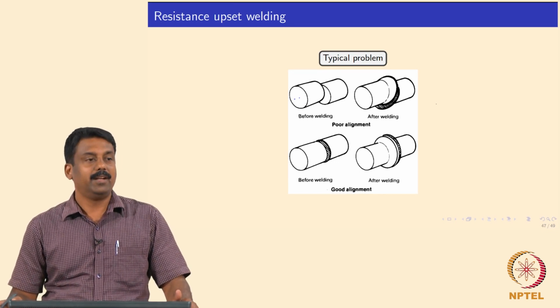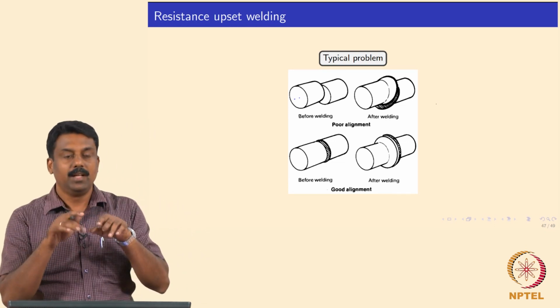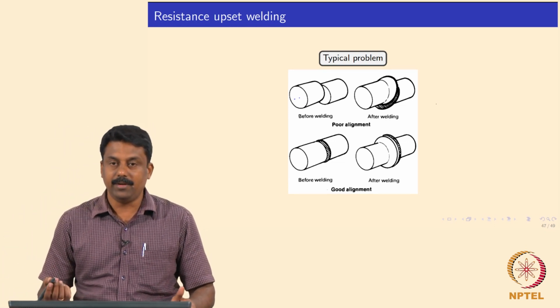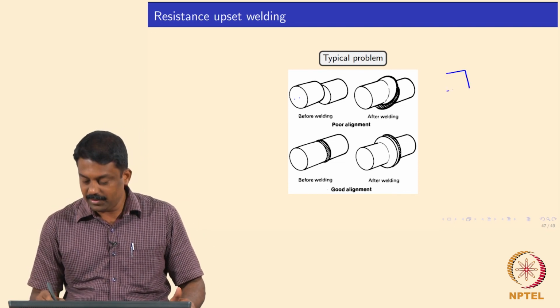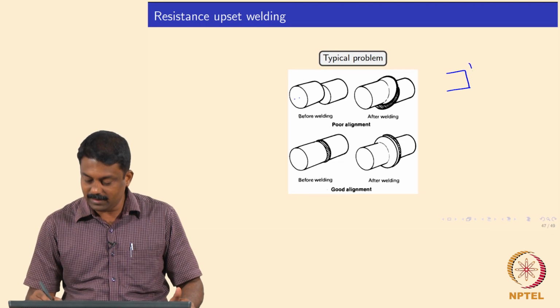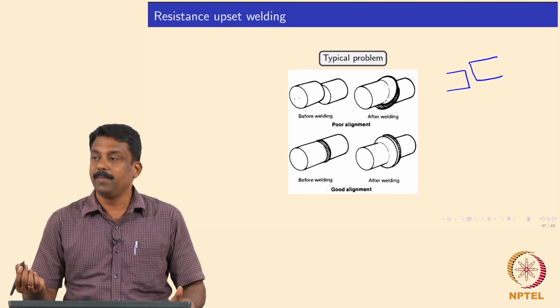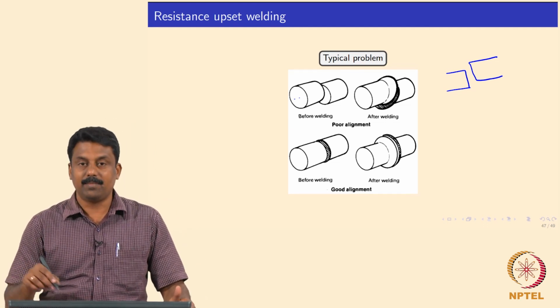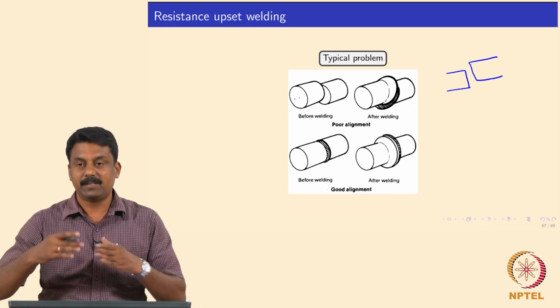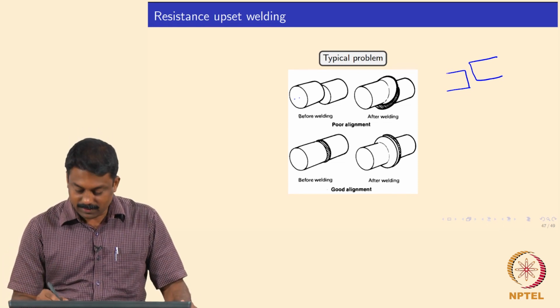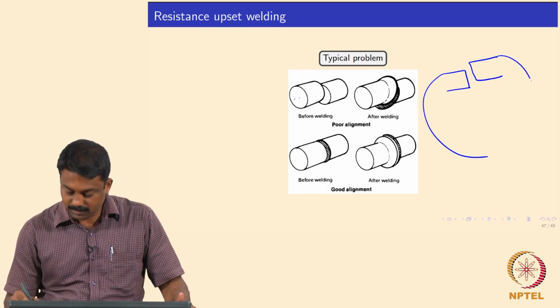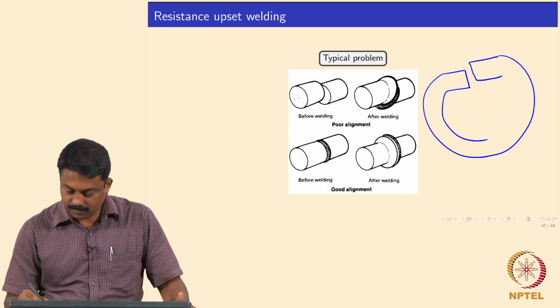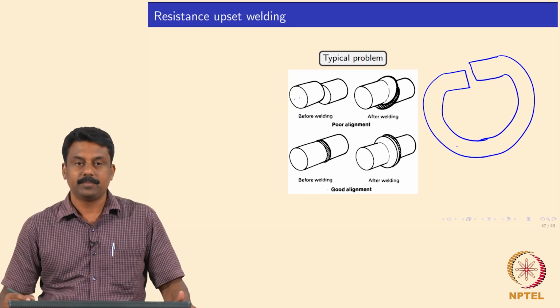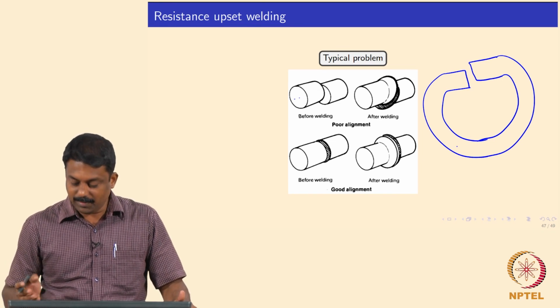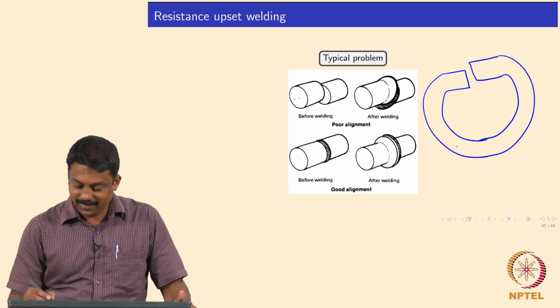And this is a very common problem even in wheel making. If there is a small misalignment and you have, say, 2 mm, 2.5 mm sheets that are commonly used for wheels, and this is one edge of the wheel, and the other edge should be perfect. If the other edge is somewhere here, because the most common problem in the rolling of circular pipes is spring back. If the spring back is not controlled properly, something like this, a cross section, it's not symmetric. Imagine this is a toy car, so the wheel is like this. Now if there is a spring back, obviously the joint will be different, isn't it?